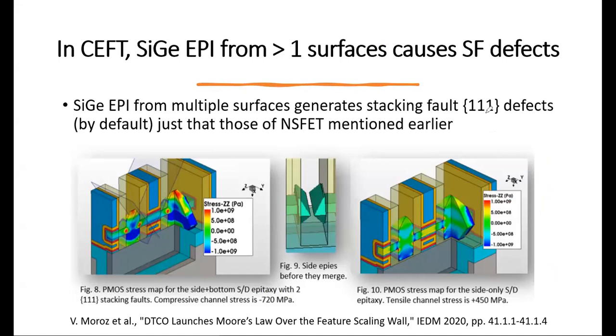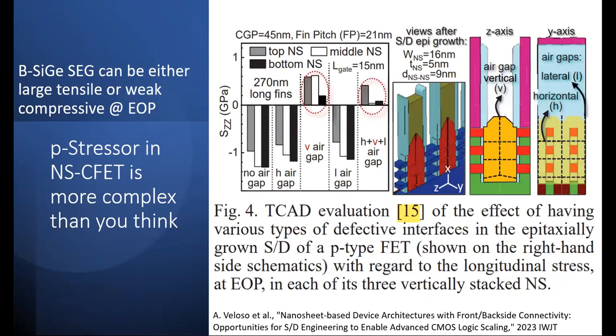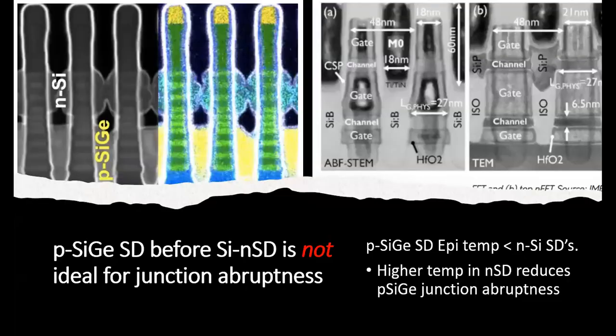The stressor now is defective, and then your silicon nanosheet channel is actually born tensile, and that's bad, right? You can imagine that's bad. And on top of that, here's the simulation from imec, which is very interesting. It says it depends on the defect, because there is the vertical stacking fault and the horizontal stacking fault, and you also have a free space here. With that, you could form, in different conditions, sometimes tensile, sometimes compressive. Compressive is what you want. But in certain conditions, you could form tensile. Imagine you have a device, and if you cannot control it, then that's a big problem. That's a big problem.